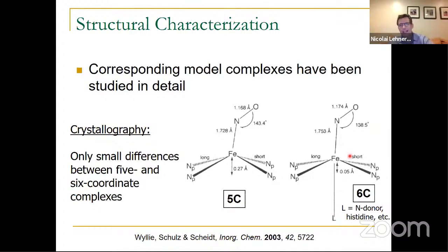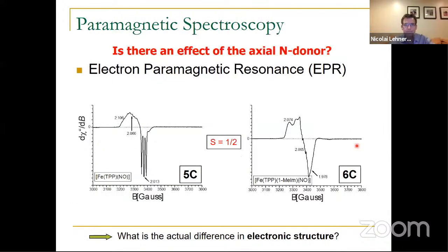So the question is, how does that now relate to the properties of the iron-NO bond, right? And how does the iron-NO bond change between the 5 and the 6 coordinate complexes? So we can study this using spectroscopy. So here's one example. You can take an electron paramagnetic resonance spectrum, an EPR spectrum, because these complexes have paramagnetic ground states. These complexes have S equals 1/2 ground states with one unpaired electron. And you can see the EPR spectra, they show some differences in their appearance. So we have this hyperfine coupling here from the NO ligand. But if you look at the g values, they are relatively similar, 2.1, 2.066, 2.01. And then in the 6 coordinate case, they're a little bit smaller. So there is some difference here in the amount of unpaired electron density on the iron,